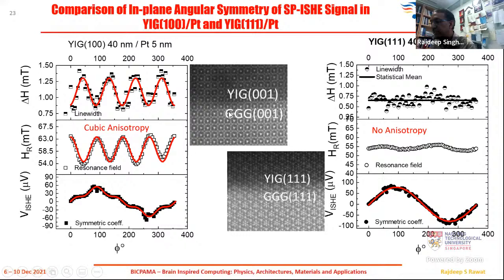If you look at the results, the cubic anisotropy, which is exhibited by YIG 0, 0, 1, actually shows the modulation of your sinusoidal curve. Whereas for the YIG 1, 1, 1, which does not have any strong anisotropy, which is also reflected once again in the HR and delta H measurement, then you see almost like a perfect sinusoid. So that is what the modeling was saying, and we saw that. But as we hypothesized, the anisotropy of the crystal system should also affect this VISHE voltage, and therefore VISHE should be modulated, and that is what is reflected over here.